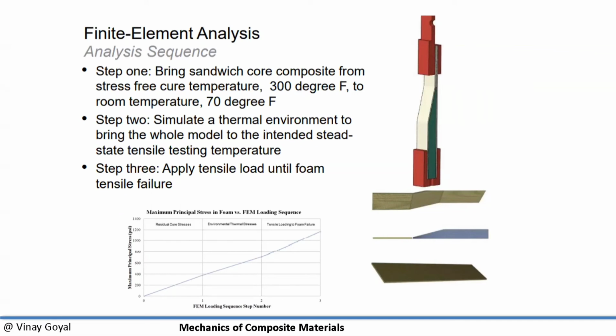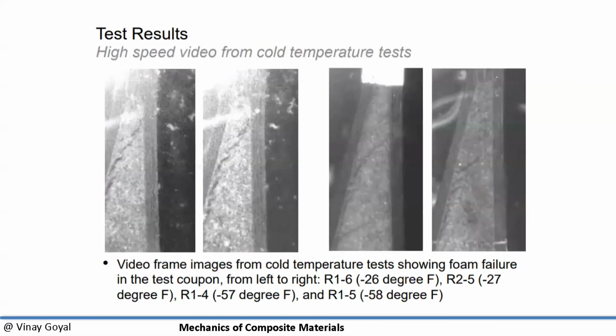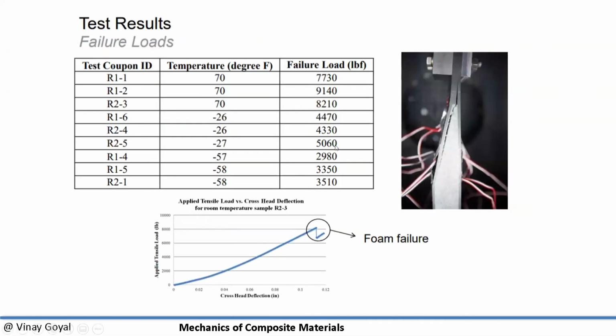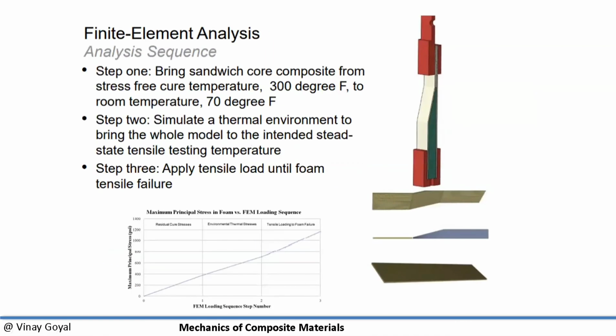The one thing I want to mention is that this residual stress can be hard to characterize sometimes. And so in this case, it had to be done because there were failures happening at low levels of load, way lower, by half, compared to room temperature. And that was unclear. But when you look more carefully, you can learn about what's going on through this process. The first thing I want to mention is that there is a stress that's developed from cure to a later point in time.